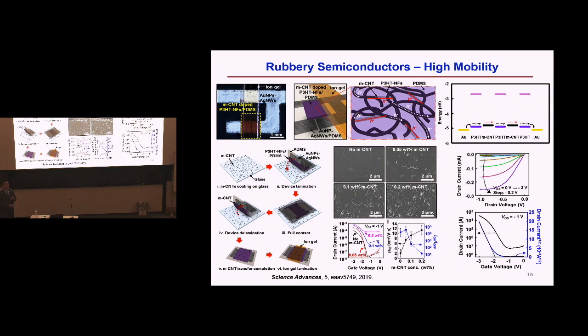Now we can design and optimize the composition of the metallic carbon nanotube. For example, if we put in more metallic carbon nanotubes, then you probably end up shorting the source and the drain. You sacrifice the off current or the on-off ratio. So basically, we came up with a way to incorporate this metallic carbon nanotube by physical fabrication methods into the previously fabricated 2 material system. Now we can add a third material, metallic carbon nanotube, and we can optimize the amount of the metallic carbon nanotube in the system, and also look into the on-off ratio and the mobilities, and we can do the material optimization.